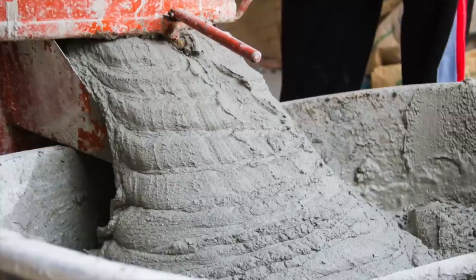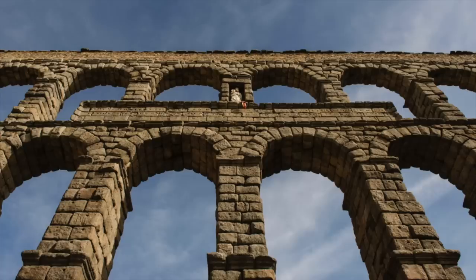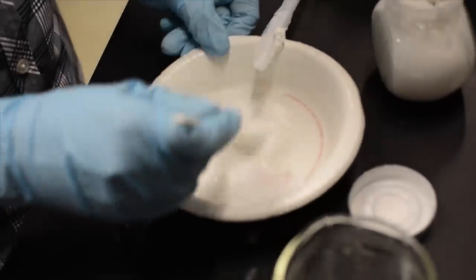The microstructure of this rock is made of mineral fibers that are called tobermorite and ettringite. Tobermorite and ettringite are minerals that are found in man-made concrete including Roman concrete. Actually Romans engineered their concrete by using the pozzolana from Pozzuoli and mixing the pozzolana with lime.